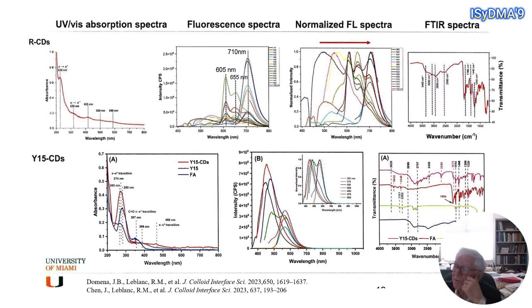And finally, to change the negativity of the carbon dots that were prepared, because all the carbon dots that have been shown up to now are negatively charged. To have positively charged ones, we need tetraaminobenzene mixed with citric acid, and using the microwave, it was easy to get the formation of the carbon dots.